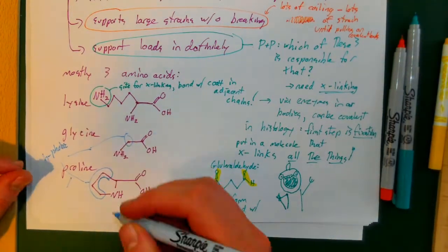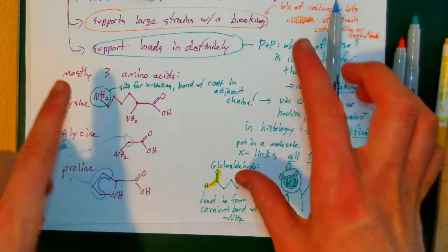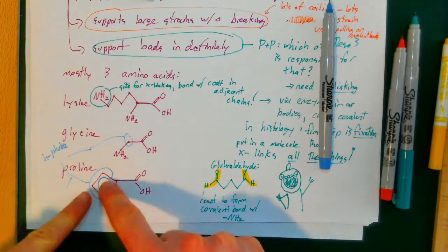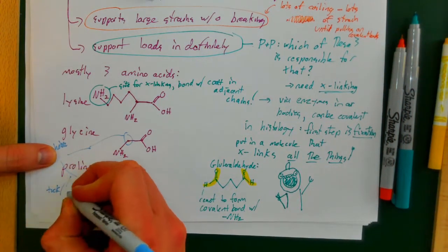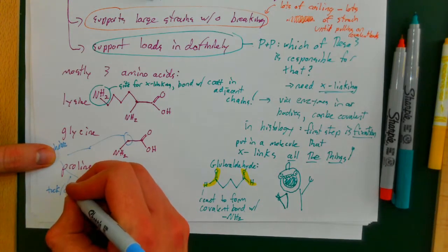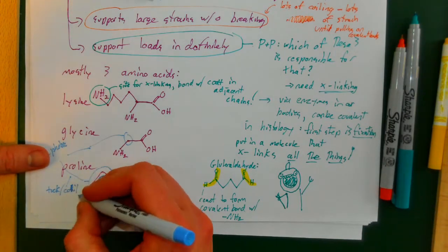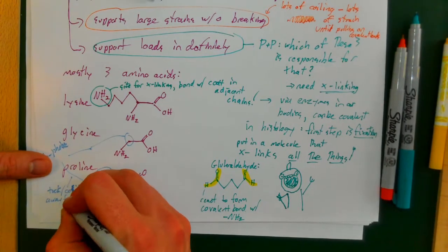And what do they do? They collapse in on themselves. Different chains of elastin will rotate and contort themselves such that they tuck all the hydrophobic regions together, away from the water in the surrounding tissue. So they tuck or coil away from water, but it's a relatively weak process that you can undo with some mechanical force.